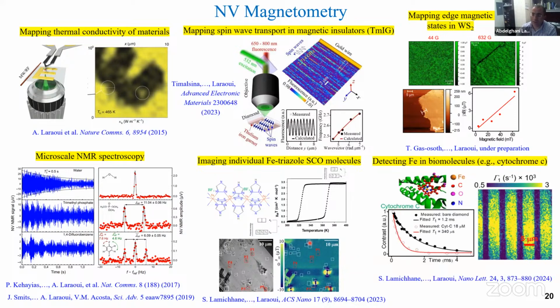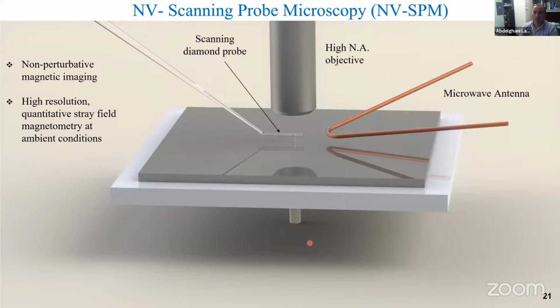And also by looking at the T1 relaxation, because this two-level system interacts with the environment. You have iron in biomolecules, and the spin noise can lead to a decrease in T1, and therefore you can image these biomolecules. So I will go into the details of how NV SPM, or NV scanning microscopy, works.